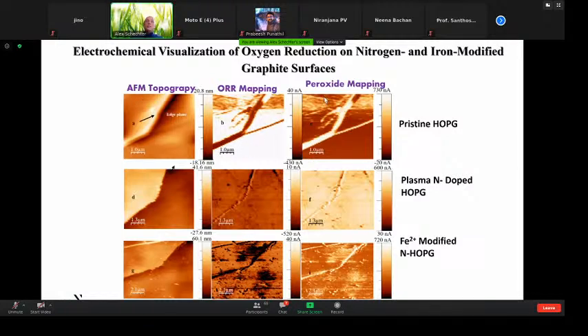And then we ran the same experiment. This time, we were looking for hydrogen peroxide. We took the tip and placed a specific potential at which only hydrogen peroxide can react. And quite nicely, we can show that the hydrogen peroxide is formed at the same location. You can see the currents coming from the same location where oxygen reduction takes place. So this is direct proof that the hydrogen peroxide is connected directly to the formation of the oxygen reduction product. You could also see some stretching and so on.